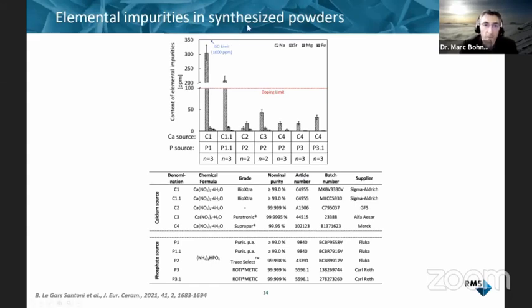The first test we did was with 99% pure calcium nitrate and a 99% pure phosphate, ammonium phosphate. And this is the result. The first one, we had 300 ppm of strontium. And Paul Bowen at EPFL always told me that any ceramic that has more than 100 ppm of something is a doped ceramic. So in that case, we would have a strontium doped ceramic.